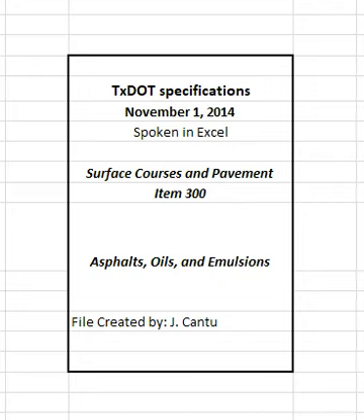6. If creep stiffness is below 300 MPa, direct tension test is not required. If creep stiffness is between 300 and 600 MPa, the direct tension failure strain requirement can be used instead of the creep stiffness requirement. The M value requirement must be satisfied in both cases. 7.